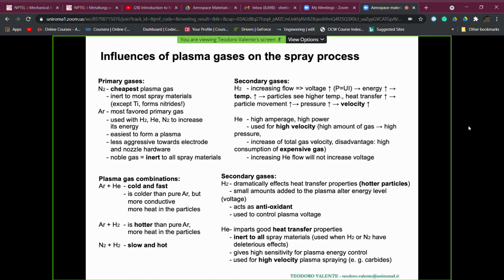And so, depending on the plasma mixture which is used, and having in mind the effects on temperature and on velocity, we need to select the proper spray distance for these selected materials. This means that if we change the plasma gas combinations and we have in mind to spray the same materials, the spray distance is not the same for all the plasma combinations, because there are different effects on heat exchange and velocity exchange on the particle itself.